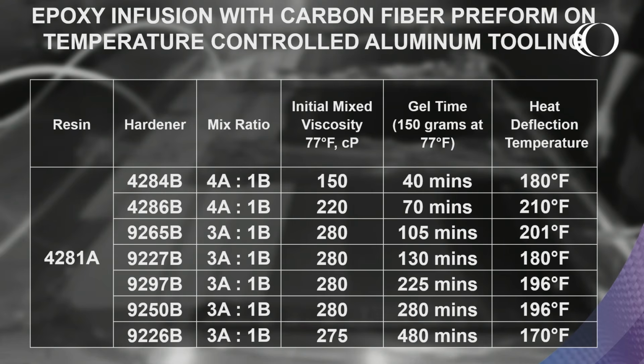And as you see, there's a universal resin with all different hardeners depending on what gel time you need, heat deflection temperature, and viscosity. So as we're doing for this smaller part here, we want to cure quickly so we can mass produce parts multiple times a day on the heated tool. So that's why we're choosing our fastest system. In addition, other hardeners that we have to offer with this resin system are for toughening, core shells, as well as FR properties.